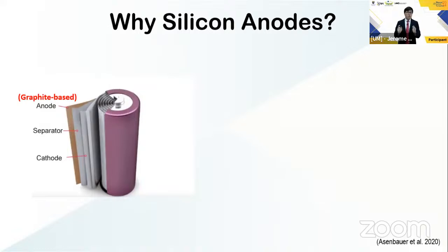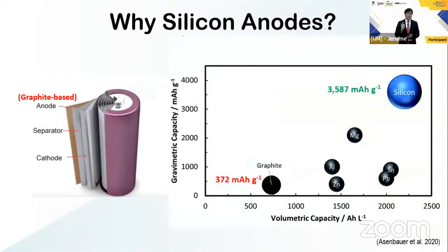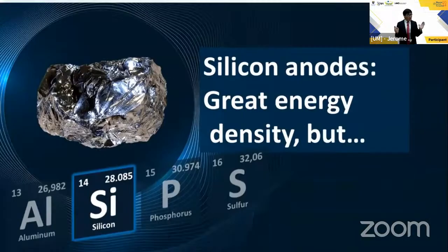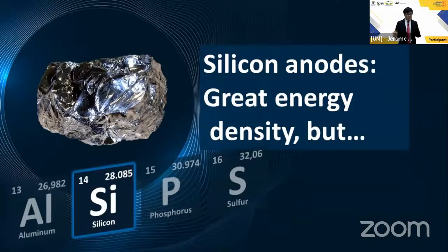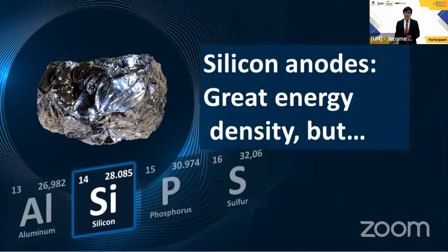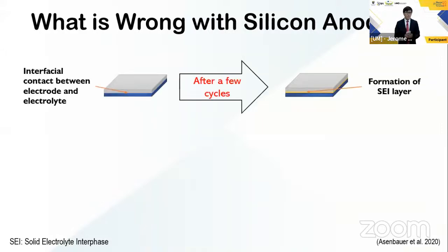Commercial batteries use graphite-based anodes, and graphite anodes have a maximum capacity of 372 milliamp hours per gram. Having said that, silicon anodes have a maximum capacity of almost 10 times that of graphite. So why are we not harvesting this potential? What is stopping us from using this? There's a reason for this, but we have to first learn about the formation of a solid electrolyte interphase.